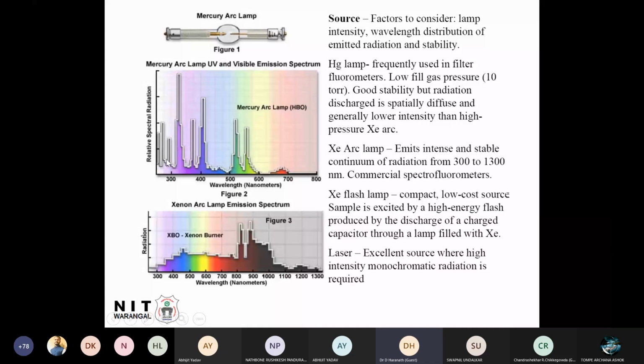Suppose your material absorbs in this region, and suppose you measure the absorption of the material you have developed, and it lies around 495. If you put it under this mercury lamp, which does not have that wavelength, your material will not glow. Then you feel that your instrument is not working, or your sample is not good.